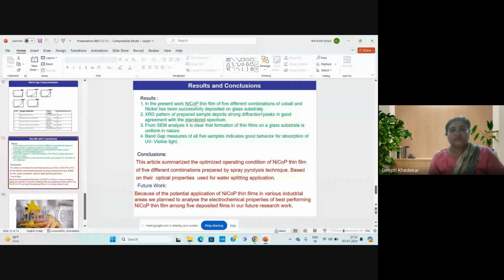Results and conclusion. In the present work, NiCoP thin film of 5 different combinations of cobalt and nickel has been successfully deposited on glass substrate. The XRD pattern of the prepared samples depicts strong diffraction peaks in good agreement with the standard spectrum. From SEM analysis, it is clear that the formation of thin films on the glass substrate is uniform in nature, and band gap measurements of all 5 samples indicate good behavior for absorption of UV visible light.